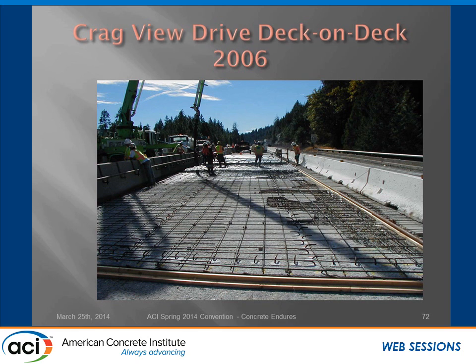We took off the riding surface and found out, oh, yeah, this bridge has ASR in it, so it doesn't make sense to put an expensive overlay on it. We need to replace that deck, so hey, we got another chance to experiment again. We actually used the same contractor that we did at Mud Creek on the previous slide, and it was the same mix design that we used at Mud Creek on the previous slide. The difference was we added some SRA to this mix design. And the other thing that we did was we were behind K-rail here, so we could have the opportunity to cure it for 7 days.